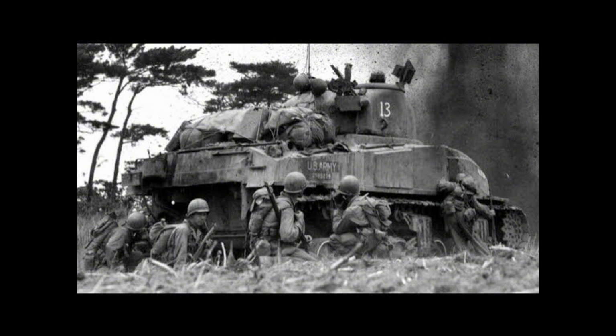Hirsch's innovation was to create what he called a gradient armor structure within a single plate. The outer face would be hardened to Brinell 340 or higher, hard enough to begin shattering the tungsten core on impact. But hardness alone made steel brittle, prone to catastrophic cracking under the shock of impact, so the interior layers would be progressively softer, down to Brinell 260 at the back face, providing the toughness needed to prevent the plate from shattering completely while still maintaining enough resistance to stop the damaged penetrator core from completing its journey through the armor.